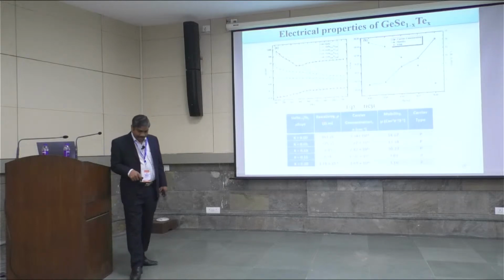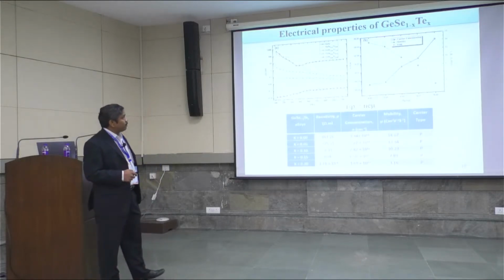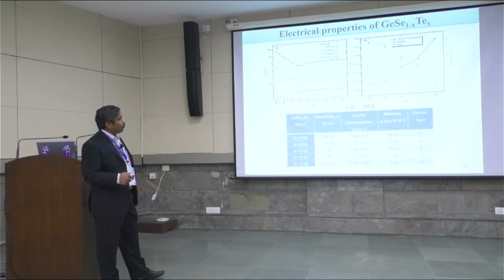And these are the transport characteristics of the tellurium substituted germanium selenide. And look at that, the pure system is relatively highly resistive, and when the tellurium content increases in the system, the resistivity decreases quite a lot, up to several orders. Right? So it was in the order of hundreds in the pure system, and when tellurium is substituted, the resistivity decreases by up to 3 orders. Then this is the variation between the carrier density and the mobility. Again, the mobility is dropping at high carrier density because of the scattering process.